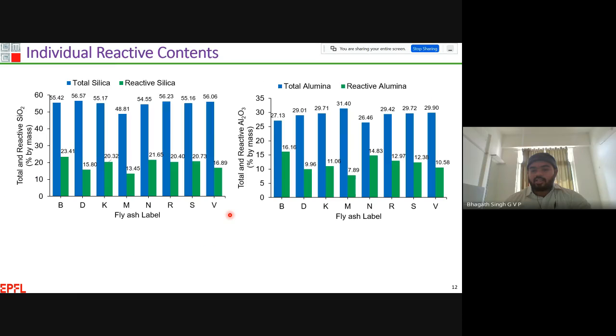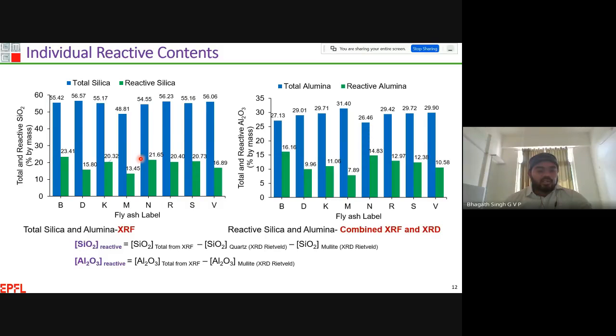Then I went one step forward. I determined the reactive silica as well as the reactive alumina content present in all these fly ashes. This is the fly ash I have represented here. These are the source locations, and the y-axis represents the total as well as reactive silica. The total silica, as I said, I determined using the XRF technique, and the reactive silica as well as reactive alumina I determined using the combined XRF XRD technique. These are the standard equations I used to determine the reactive silica and reactive alumina.